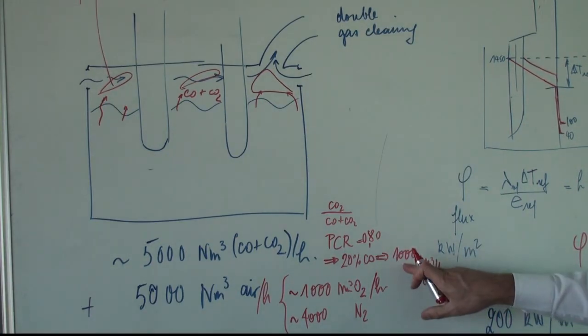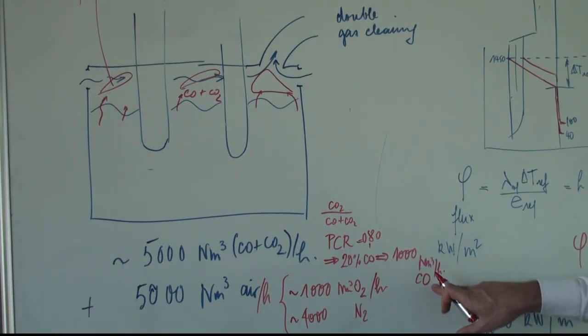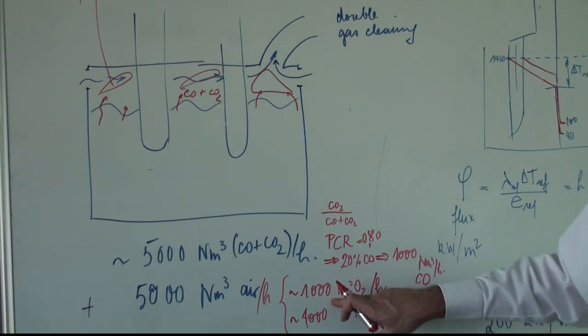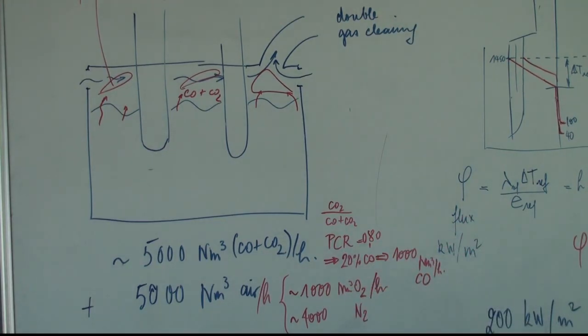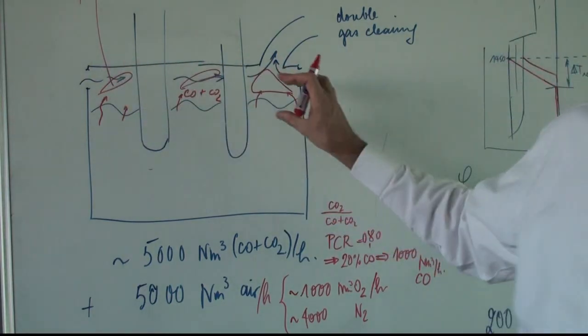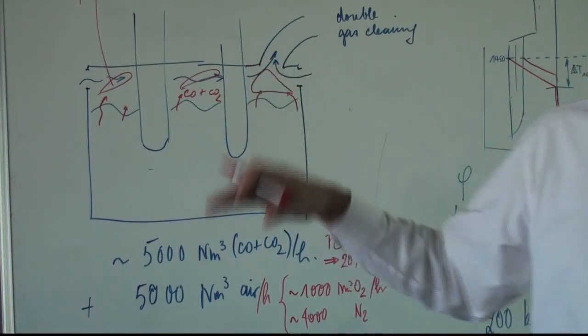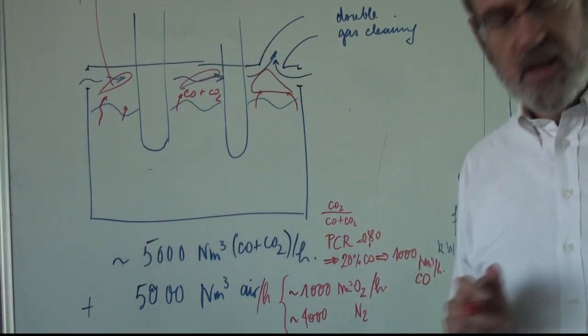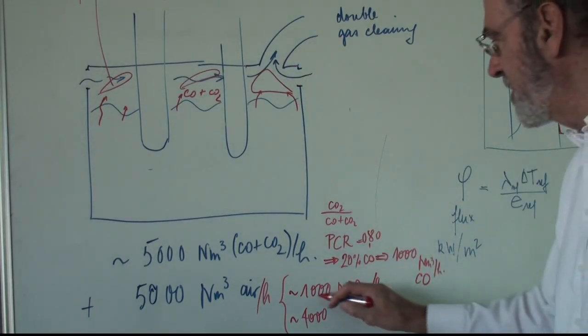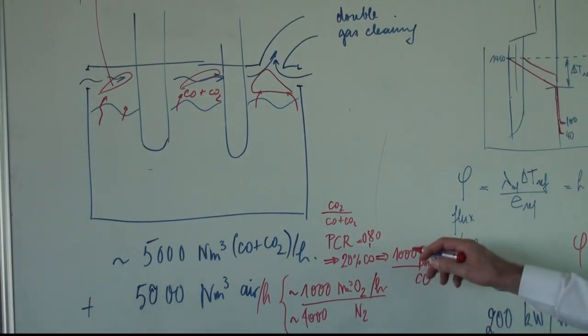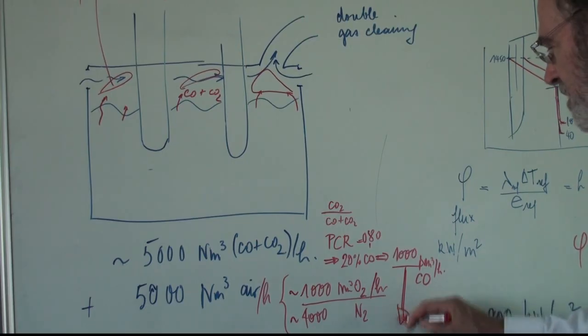And look, to burn 1,000 cubic meter CO, how much oxygen do I need? Half, exactly. So I have more than the required oxygen to burn the CO. You can be sure, because it's not an organized burner at this area of the furnace, but having much more oxygen than required, you can be sure that you will burn all the CO here. So you see, this is more than half of this, so all burned.